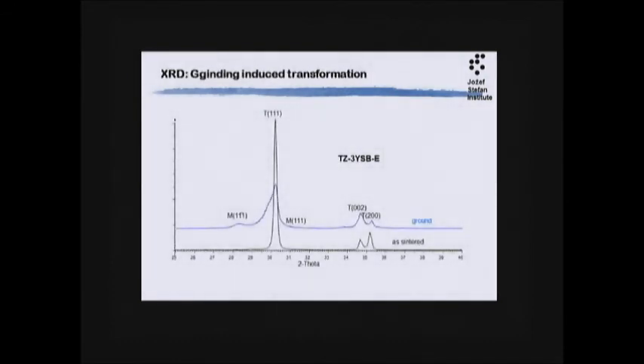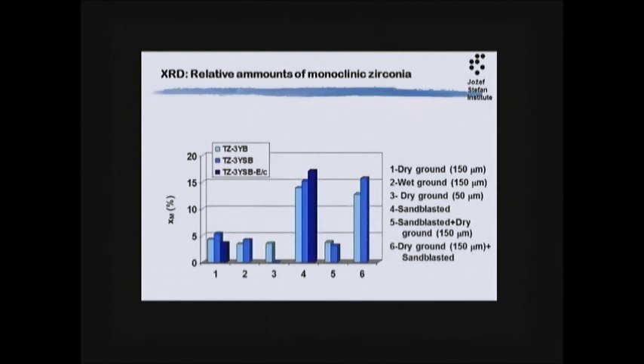X-ray. I'm sure I'm bothering you, but the X-ray pattern will change quite dramatically from the initial material with a very sharp peak and two peaks here. Then we start seeing this one, which is the monoclinic after grinding or sandblasting. This one will get distorted. It will shift, and this is again something ignored in the aging story. And the intensity of these two peaks will be reversed. Anyway, enough to think about it. It's not just